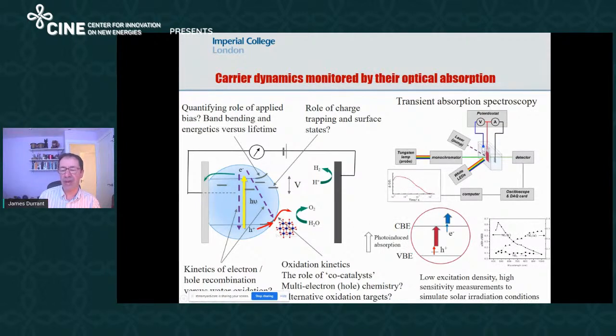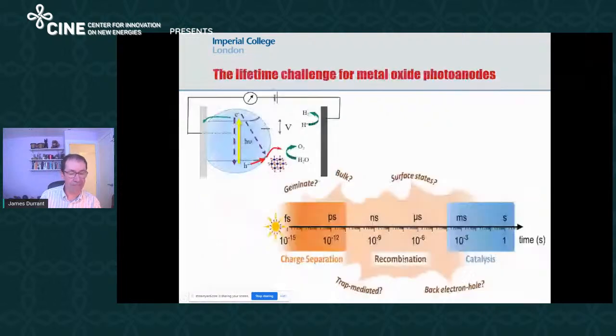And the way we do that is with spectroscopy, and particularly operando spectroscopy. We take our material of interest, put it in water and apply a potential to it, shine light on it, and try to measure the kinetics of electrons and holes by measuring their absorption, the changing color of the sample due to generating these carriers, as a function of time after excitation. And so you can see some optical signal as a function of time, which gives you an idea of how long-lived holes or electrons are in the material, and you use that to try and understand function.